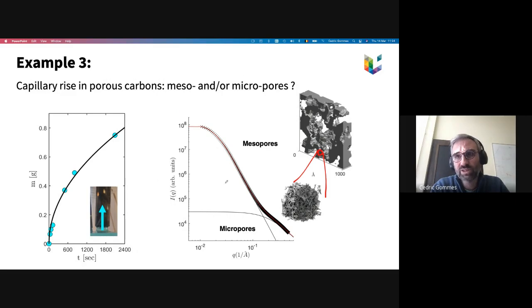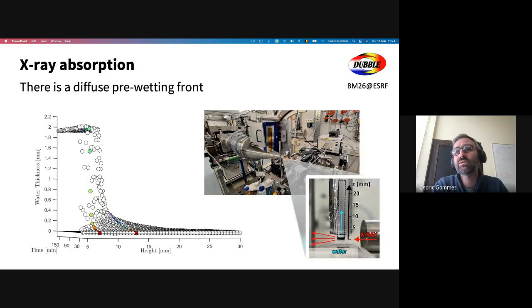And so we did these experiments where we had basically the capillary rise experiment. So here is the porous carbon area. It's wrapped in aluminum foil to prevent side evaporation, and we are shining X-rays through it while the water is climbing up, yeah? And we're scanning up and down, up and down, up and down, yeah? Over a matter of about 1 hour.